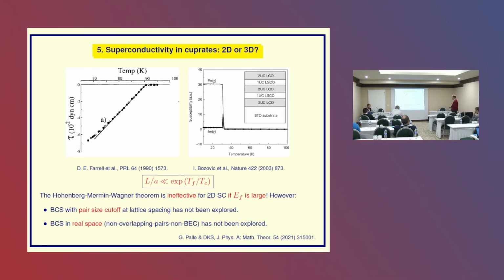But the special thing is, there is a wonderful little experiment very early on, actually a torque experiment, which shows that the material is becoming more two-dimensional as you go down in temperature. Okay, so the high Tc's are more three-dimensional around Tc than at 10 Kelvin. Okay, and so there is an intrinsic two-dimensionality.